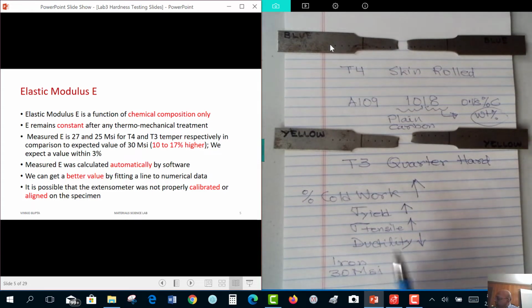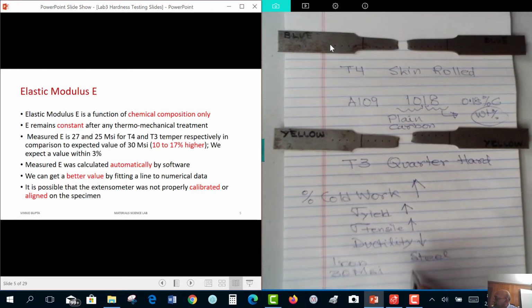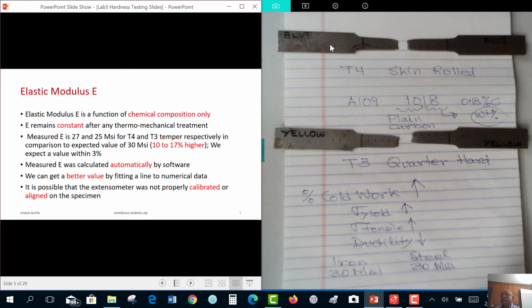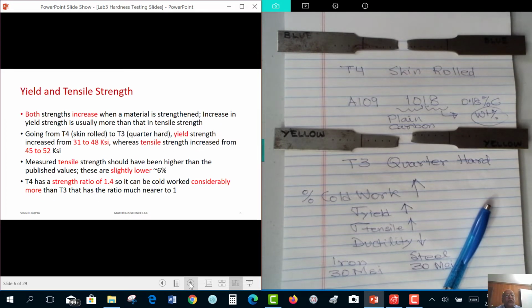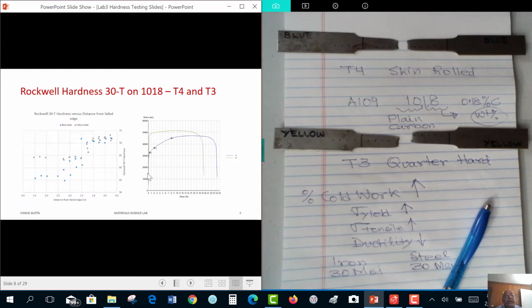So obviously when we go to this 1018 steel, we don't change its elastic modulus. It remains pretty much 30 million psi. Unless we add lots and lots of carbon and other alloying elements, we are not going to change the elastic modulus much. Now our measured elastic modulus was 27 and 25 for T4 and T3. We expected it to be about 30 MSI. This is a pretty high difference. We expect the value to be within 3%. Now, in our case, the measured elastic modulus that I mentioned in this table, these two values, were measured automatically by the software. So if we look at this curve, the software just picked up 2 points here, drew a line, and calculated the slope.